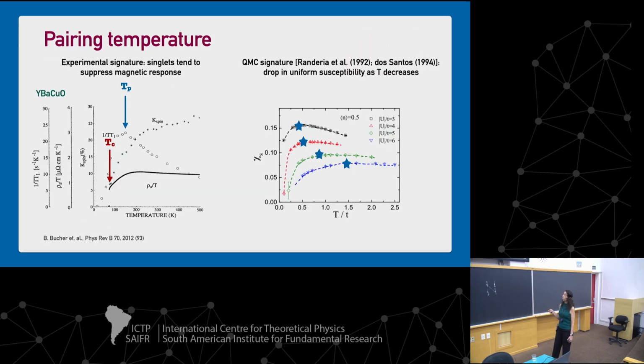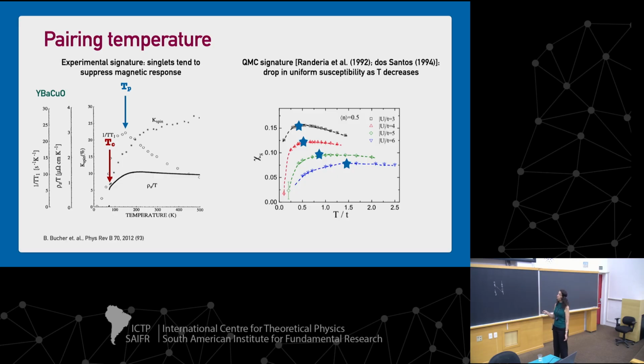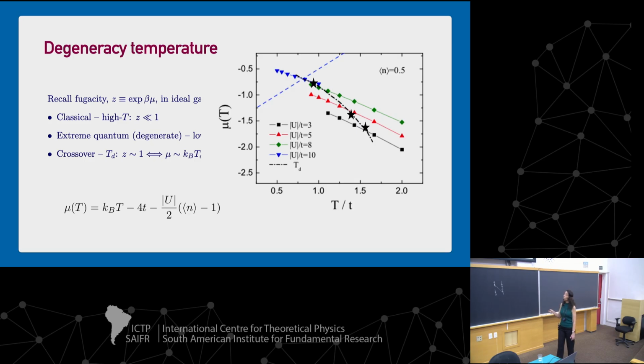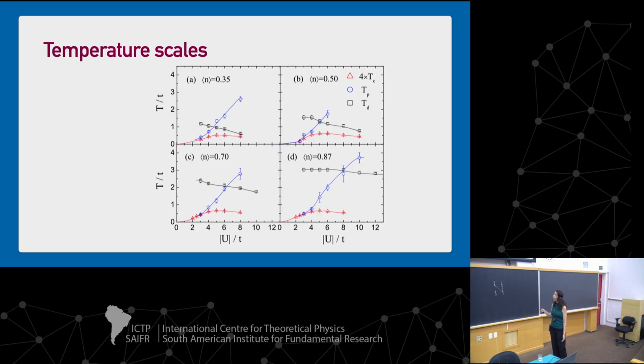But there are other temperatures that are interesting. The first one we looked into is the pairing temperature. We know that in the BCS phase, we see the pairing forms, and then they cohere. And so finding the temperature at which we have pair formation was also interesting. So in experiments, what they do is look at the susceptibility, where it starts to go down, pairs start to form. So this is what we do here. We calculate the susceptibility, and the stars are at the maxima. And we also wanted to look at the degeneracy temperature.